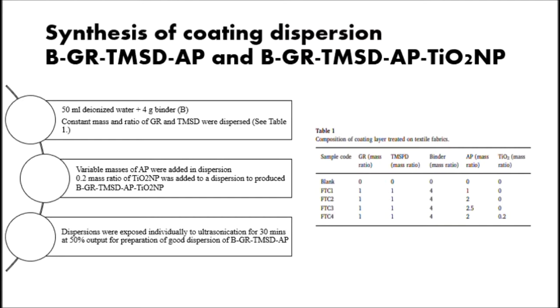For the last sample, FTC4, we added 0.2 mass ratio of TiO2 NP. After that, the dispersions were exposed individually to ultrasonication for 30 minutes at 50% output for preparation of good dispersion.